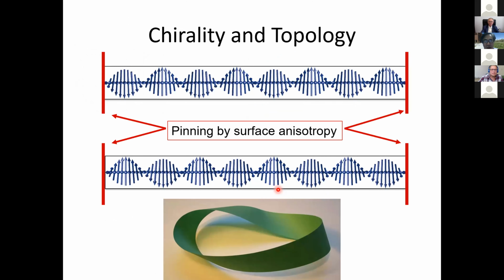Then let's consider the spin system. Here we found, almost 10 years ago, the chiral spin system. In our system, let's say the right-handed material is the upper side, and the left-handed material is the downside. We already found the helical spin structure inside the chiral magnet, but in this case we have surfaces on both sides. The spins are pinned by the surface anisotropy. In this case, we cannot convert the upper state to the lower state. So this is a topologically spin-ordered state protected by chirality.